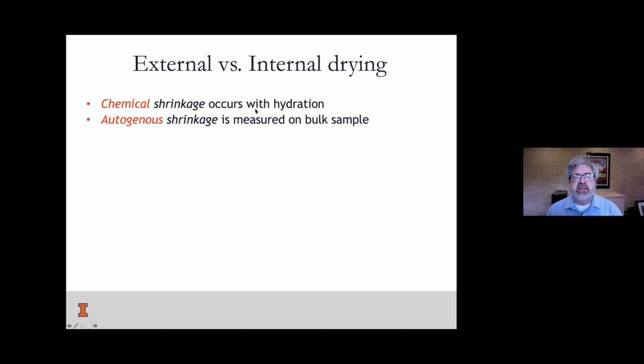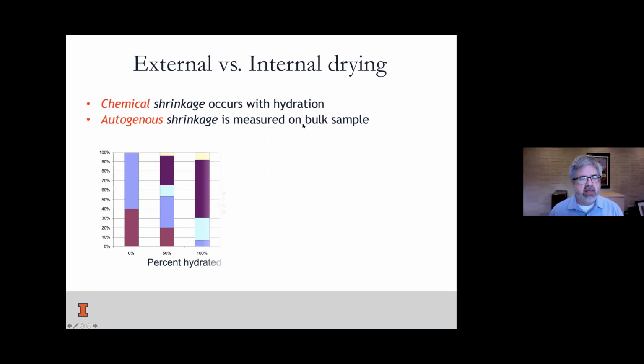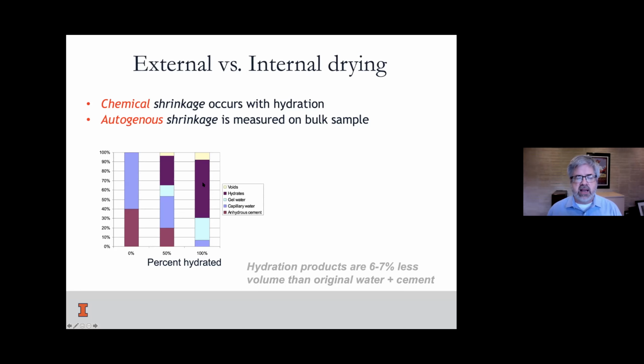So external versus internal drying. Chemical shrinkage occurs with hydration. Autogenous shrinkage is measured on a bulk sample. And this is a very commonly used chart here, where you see originally at 0% hydration, we have just capillary water, the blue, and we have the cement, the red. And now as we move to 100% hydration, we have the hydration products and so forth, but we have something here at the top, voids. This goes through a 6 to 7% reduction in volume in the hydration products compared to the original water and cement volumes, okay? That reduction is called chemical shrinkage, and it's just part of the reality of our system.